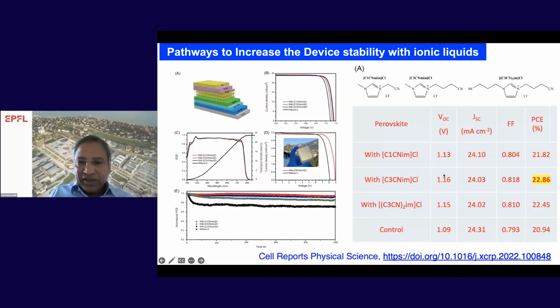By measuring the photovoltaic properties, you can see with the long alkyl chain, this propyl cyanide group gives the efficiency close to 23%, and the remaining ones are lower, and the control at the same time is close to 21% efficiency. However, if you look at the stability data, with this ionic liquid as additive in the perovskite solution, up to 1000 hours of stability measurements, you can see a significant enhancement compared to the reference sample, that's the black line.